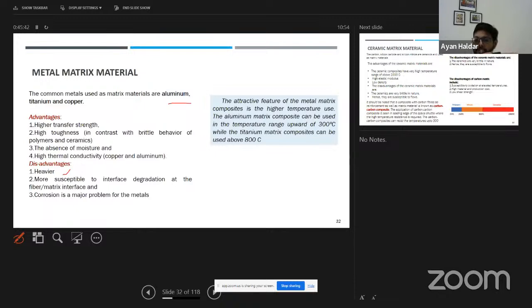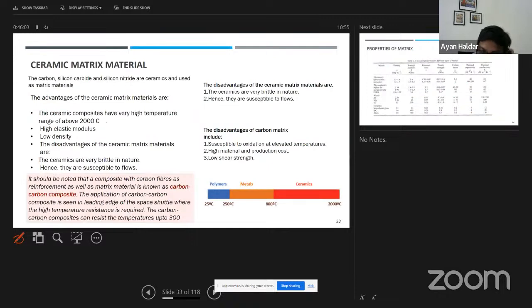Okay, so one attractive feature of metal matrix is the higher temperature use. The aluminum metal matrix composite can be used in the temperature range of 300 degrees, whereas the titanium matrix can be used above 800. So these have some applications where you really need these high temperature requirements. Similarly, ceramic matrix can be used, as you know, for even higher temperature, right? So their application also goes to around 2000 degrees centigrade. Now they have high elastic modulus, they have low density. On the other hand, the main disadvantage is they are very brittle in nature. Okay, and they are susceptible to flaws.